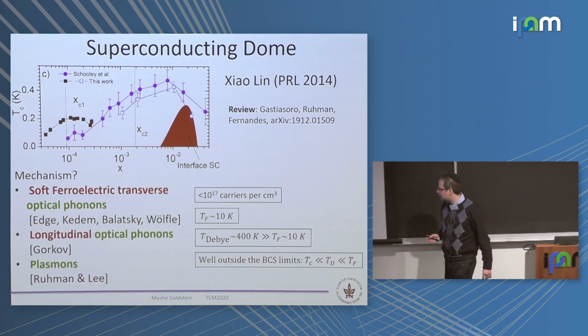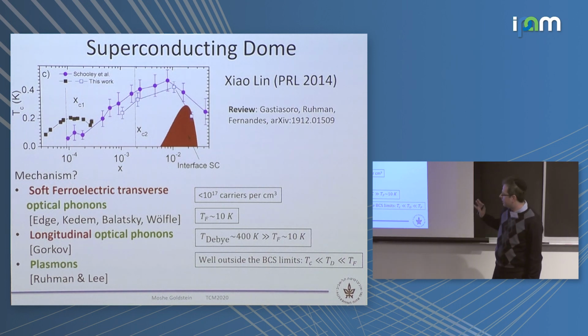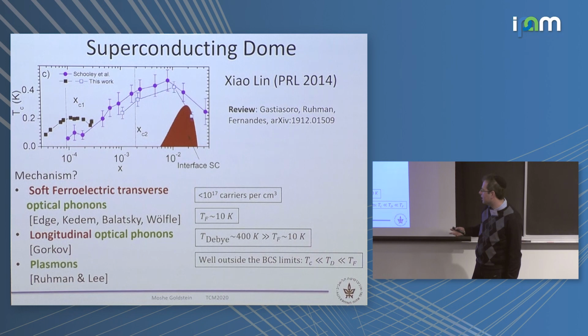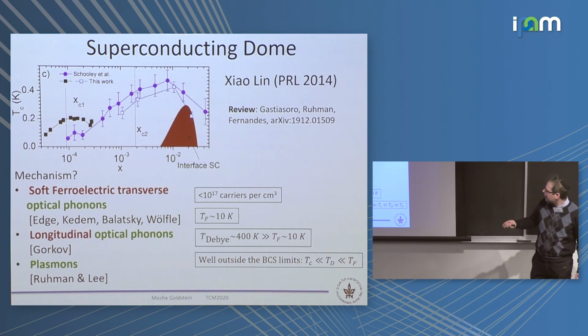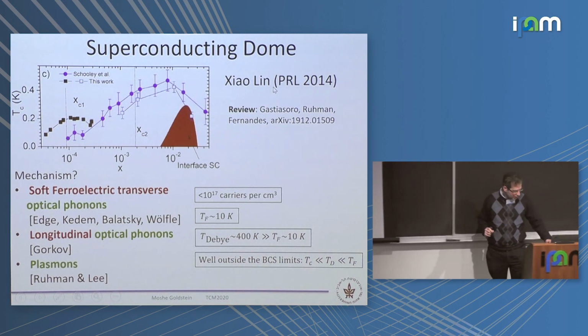And there is actually a big ongoing debate about what's making that superconductor. So people have suggested that maybe it's a soft ferroelectric transverse optical phonon. So the material is almost a ferroelectric, so there is some phonon mode which is becoming very soft, so maybe that is the glue for superconductivity. People have also suggested longitudinal optical phonons, or maybe purely electronic plasmons. And there is a big debate, because for all of those things, if you try to estimate the coupling constant, it tends to be too small. Another problem is that because you are outside the usual limit, the usual theoretical tools, the Eliashberg theory, do not apply. And I personally believe that maybe some combination of these is responsible, but this is still debated. And a nice unbiased review is this recent review, where you can read more about it.